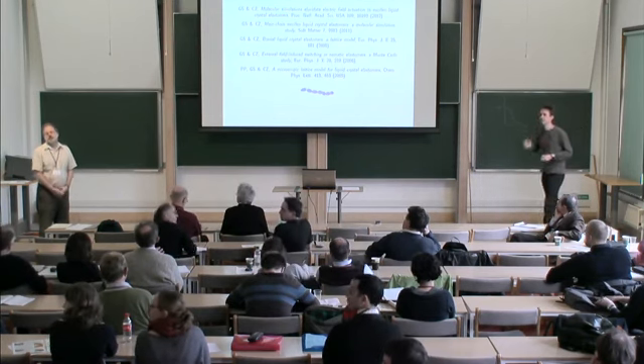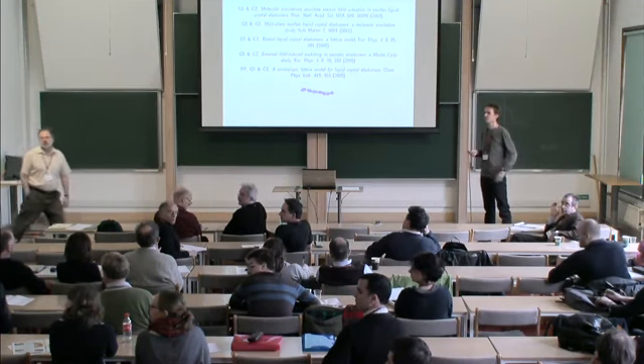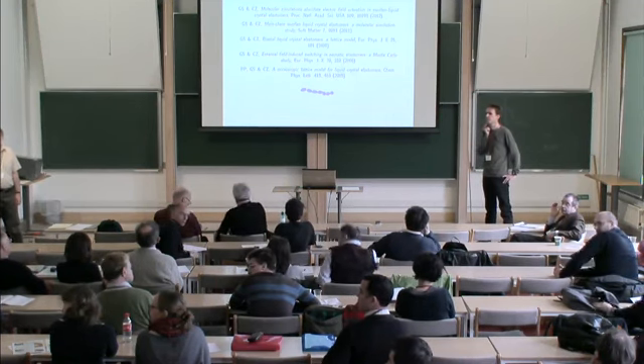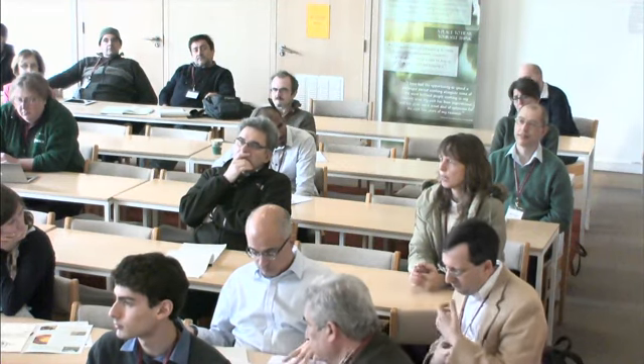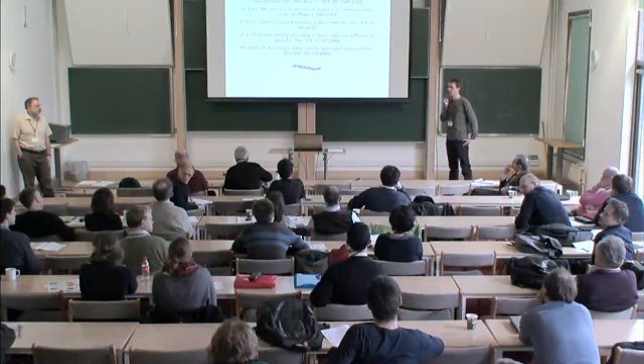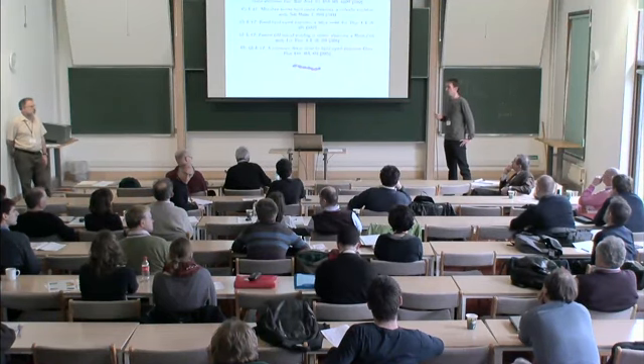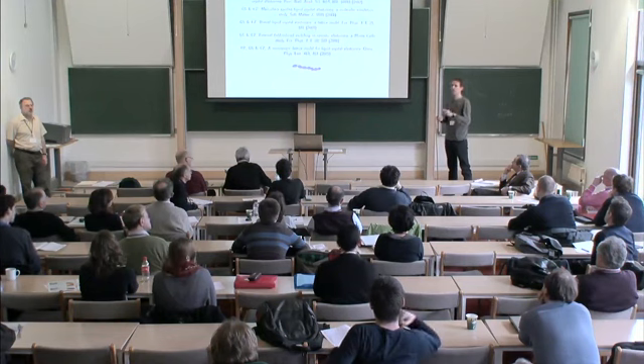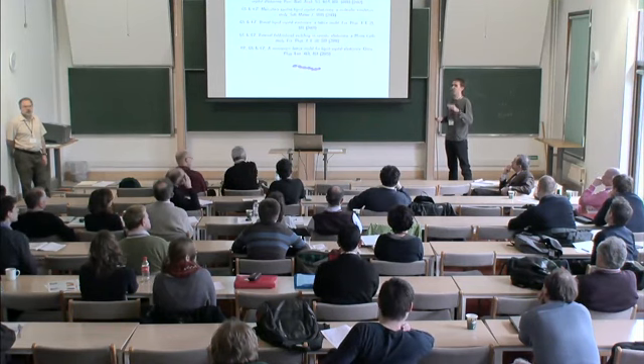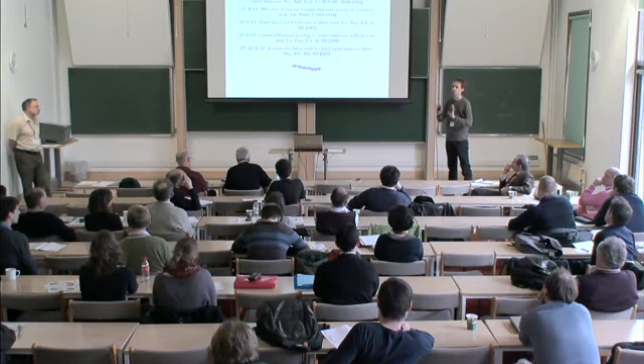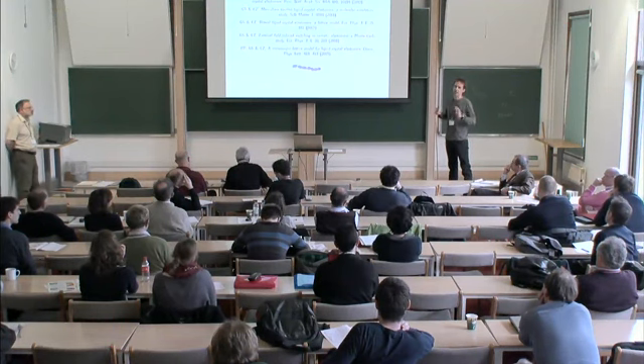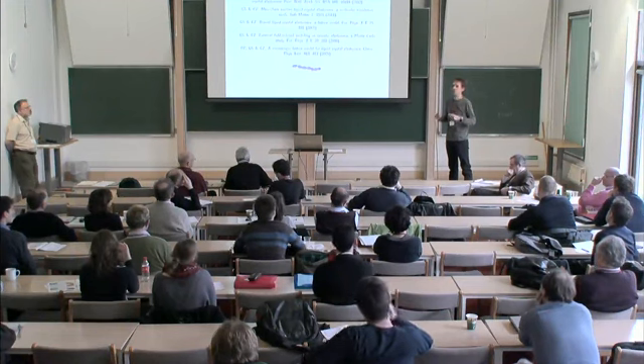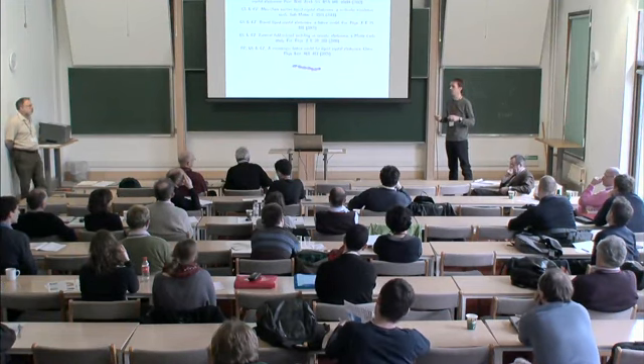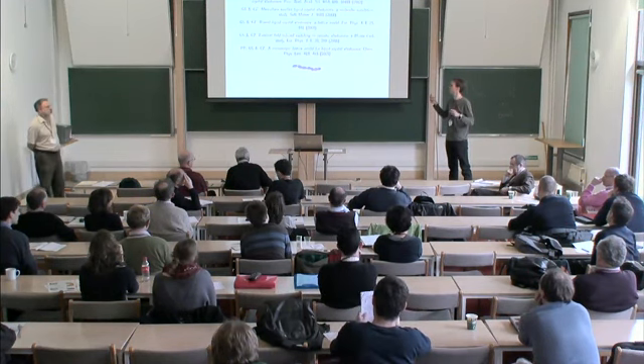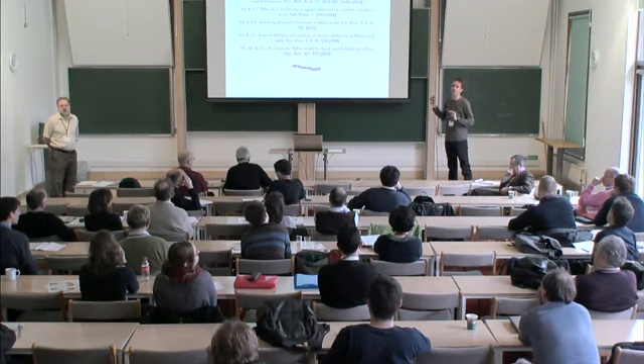Friederike: If you apply an electrical field, why doesn't the same thing happen as if you apply a mechanical field? Is there an intuitive explanation for that? Okay, so the electric field will act on each molecule individually, so it has access throughout the whole volume. The fact that we were not able to achieve the same goal by applying a mechanical field, I believe, is just related to the slightly artificial architecture of our networks.